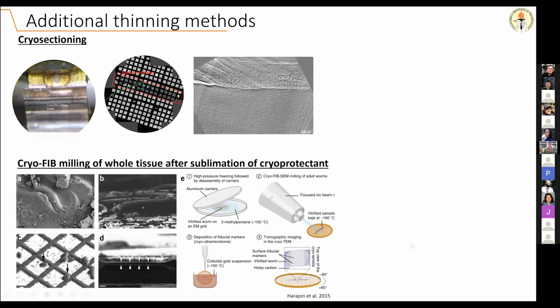Another kind of exotic technique was to do cryo-FIB milling into a high pressure frozen sample that was embedded into a cryoprotectant that could sublimate at cryogenic temperatures. And so when we sublimate this cryoprotectant, here it's a C. elegans worm, it is made available for the FIB milling.